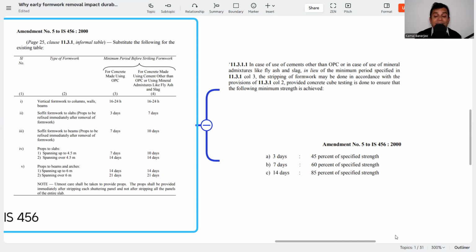So what is that criteria? If it is 3 days, you need to ensure that 45% of strength has developed. So if it is M40, 45% is 18 MPa, which has to be achieved in 3 days. If it is not, we cannot remove the formwork. Again, if it is 7 days, it is saying 60% has to be achieved. For M20, 60% is 12 MPa. The minimum strength of the cube on that day should be 12 MPa, so that you can remove the formwork. And if it is 14 days, then 85% has to be achieved.